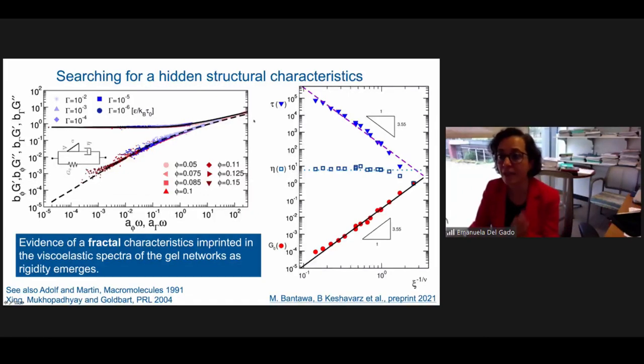And it's by doing a very systematic analysis on all the structures that we realize that in fact there is a fractal characteristic in this network, but it is hidden and buried in the rest of the structure. And it emerges as the material starts to become rigid, because this power law regime is set at the very beginning, at the transition from non-rigid to rigid, and it is set by the first rigid backbone that emerges during gelation. So there is a kind of memory of the gelation process that is imprinted in this type of viscoelastic behavior that can recapitulate the behavior of all these networks. And when we put these gels on this master curve, it points to time scales and energy scales in these networks that all scale in a way that we can now rationalize in terms of these fractal characteristics.